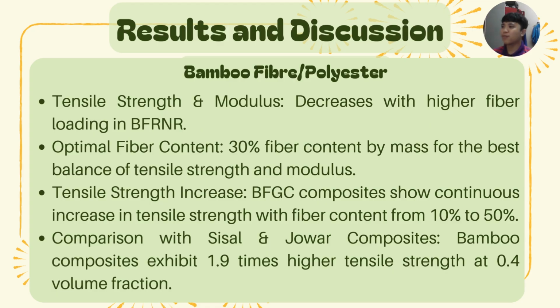Moving on to bamboo fiber polyester, tensile strength and modulus decrease with higher fiber loading. Optimal fiber content is 30% by mass for the best balance of tensile strength and modulus. Tensile strength increase: BFGC composites show a continuous increase in tensile strength with fiber content from 10% to 50%. Comparison with sisal and jowar composites. Bamboo composites exhibit 1.9 times higher tensile strength at 0.4 volume fraction.